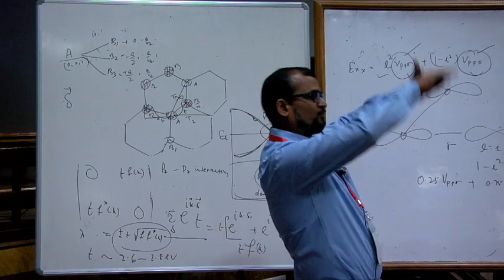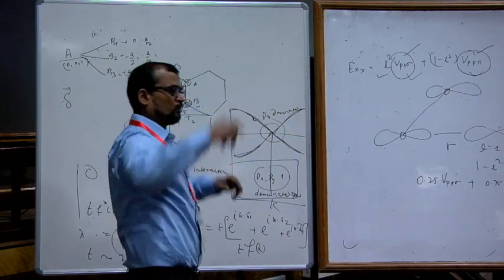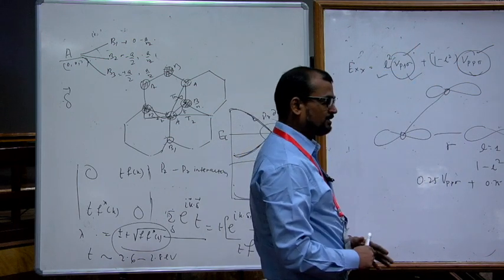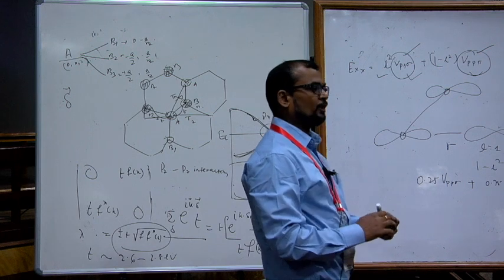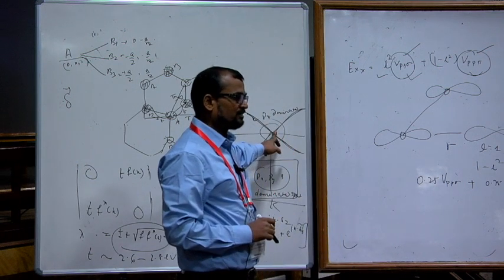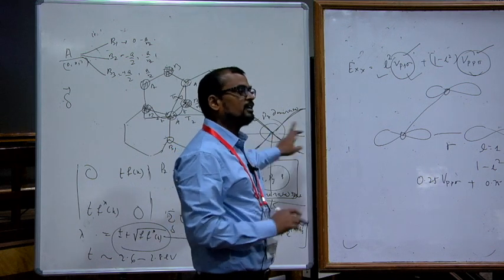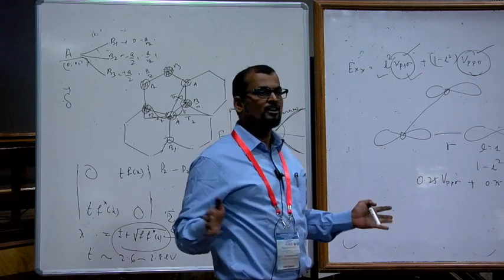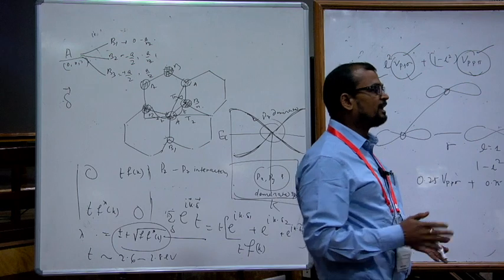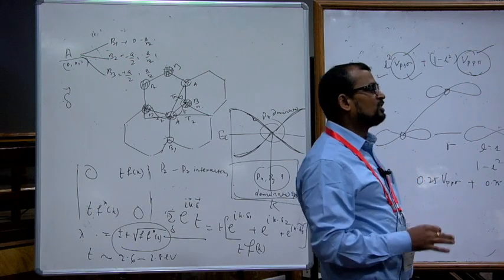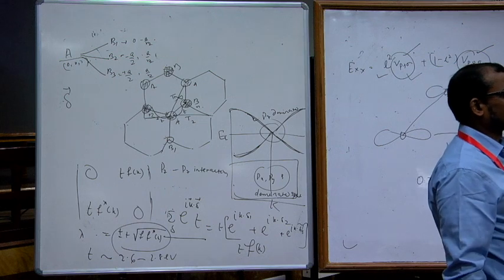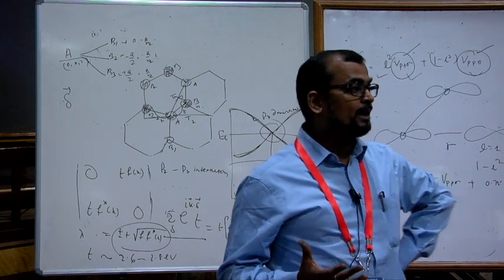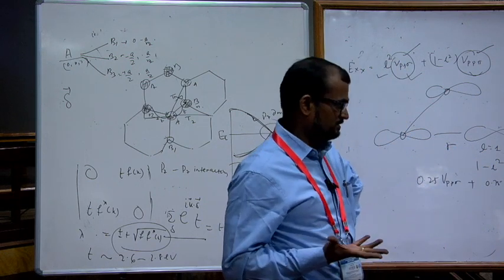Okay. Also, if you do a full-fledged study, go to second or third or fourth, then you will see that no matter what the interaction of second or third or fourth neighbor, your linearization at this point and touching of the bands at this point doesn't go away. Then you tend to tell that, yes, I understood the physical interaction mechanism in the system. The Dirac behavior appears just because of the nearest neighbor interaction. So this kind of physical description or mechanism, you can extract from these simple tight binding models.